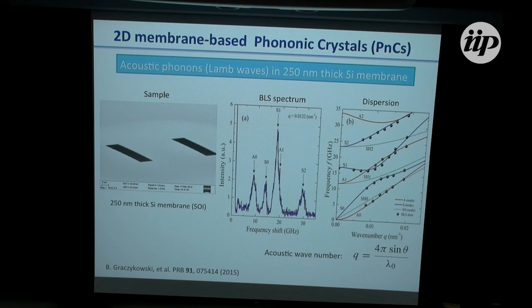First of all, this is a membrane, so no phononic crystal here. Our membrane is made in a way slightly different from what Johnny Ahopelto mentioned. We actually open some holes to allow the etching of the underlying silicon dioxide and have it suspended. It is about 250 nanometers thick. It is a silicon-on-insulator starting wafer.